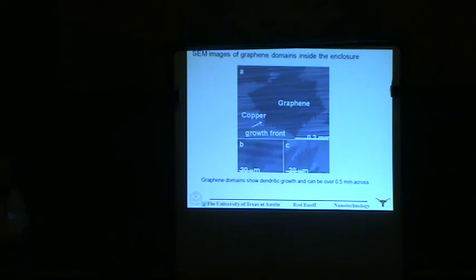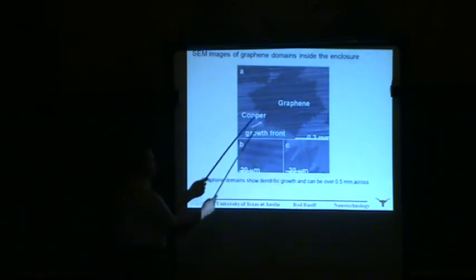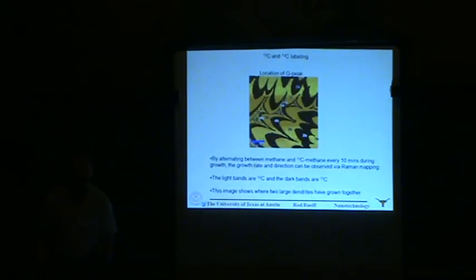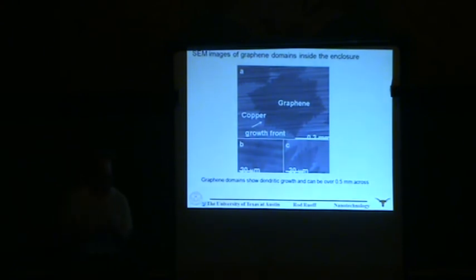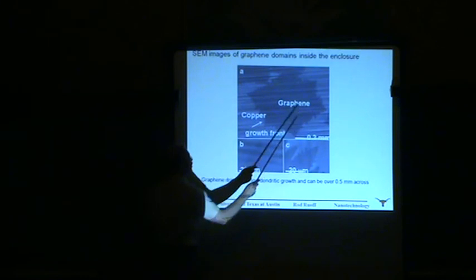And we've gone in just a couple of years from grain size of a few microns up to millimeters now through playing around with the parameters. I think you can appreciate it in terms of strength and perhaps thermal conductivity. At some point, grain size is very important because of weakness at the grain boundaries or scattering of phonons at the grain boundaries. So one of our interests is to try to grow the largest grain material we can. In this work, we had to question whether these were single crystals or not. One thing we did, again using isotopic labeling, let's talk about what Gary had mentioned, a zipper mechanism. I can tell you that the copper surface is very rough. It's highly faceted at 1,000 degrees Celsius. And we have the question, when we have these two different lobes, like this here and this here, growing outward, in the regions where they merge, what's happening?